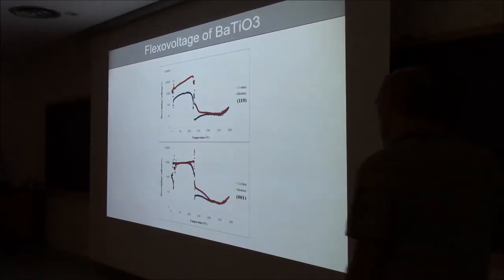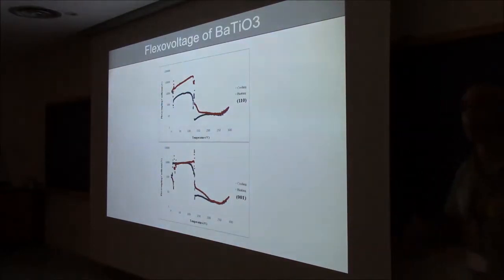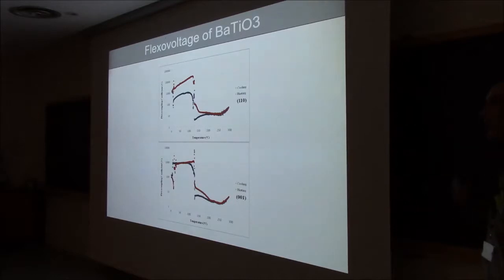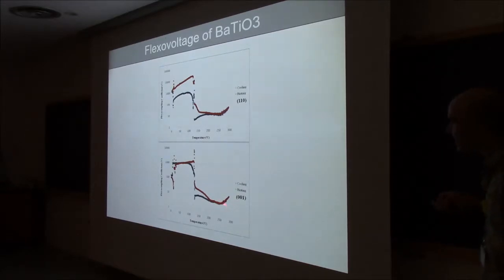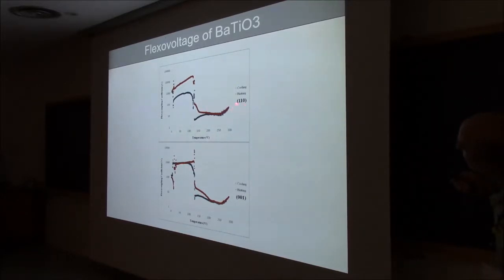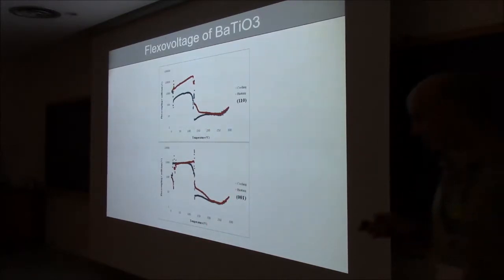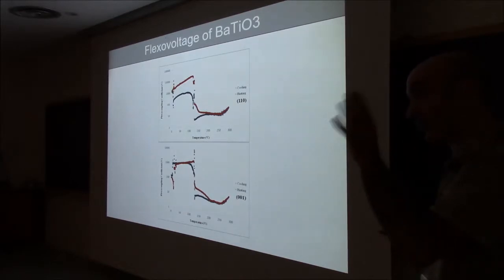So there are some phenomenological calculations that Tagantsev did a while ago, and he expected that the flexocoupling coefficient should never be a number much bigger than about 10 volts, and indeed for BTO it's not much bigger than about 10 volts. So anything that is bigger than this is coming from extrinsic contributions, polar nanoregions being one, piezoelectricity being another, but also you can see that there's a strong orientation dependence of this flexocoupling coefficient. And that's not completely trivial because the material is cubic.